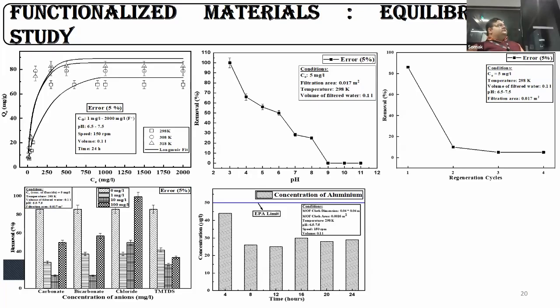We carried out analysis with anions, choosing carbonate, bicarbonate, and chloride, along with TMTDS, which is tetramethylthiuram disulfide, also named thiram, present in pesticides. We found that at increased concentration, chloride ions can start hampering the MOF, competing for the MOF anchorage sites for fluoride.